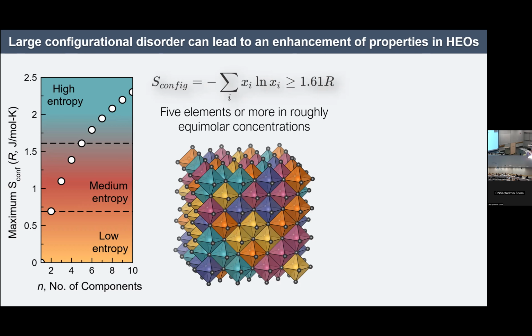One is that if we look at a typical Gibbs free energy equation, with an enthalpy of formation and an entropy term, and we want the entropy term to dominate over the enthalpy term, the typical energy scale where that happens is around when we cross from 4 to 5 elements. That's when entropy can, at typical synthesis temperatures, begin to be larger than the enthalpic term, meaning that entropy can actually choose the crystal structure the material forms in instead of enthalpy. So that's one energetic argument for why 5 is special, but that's just true on average.